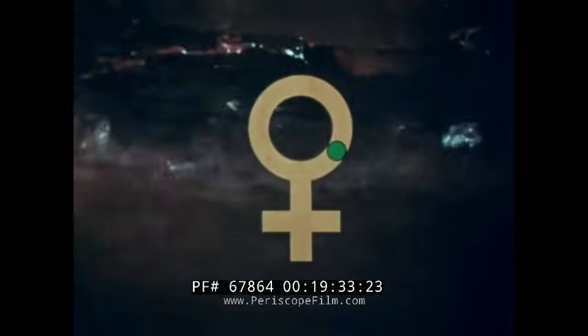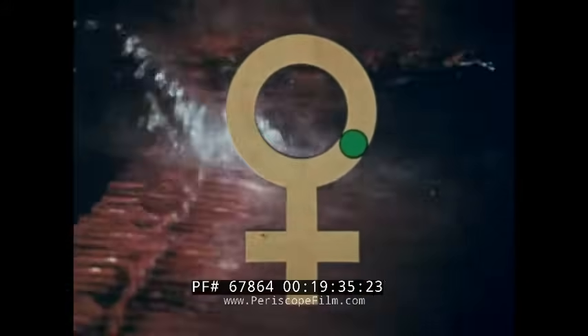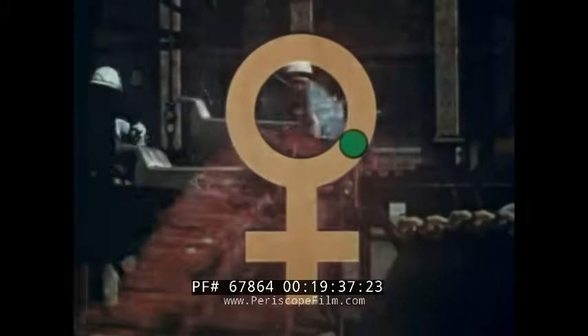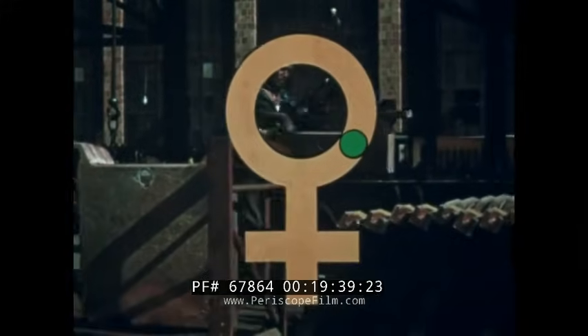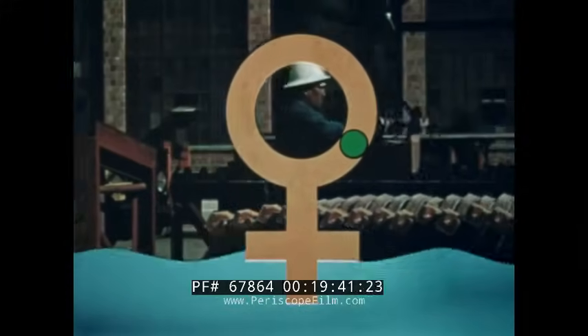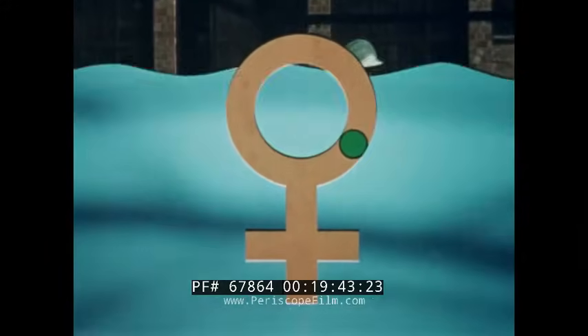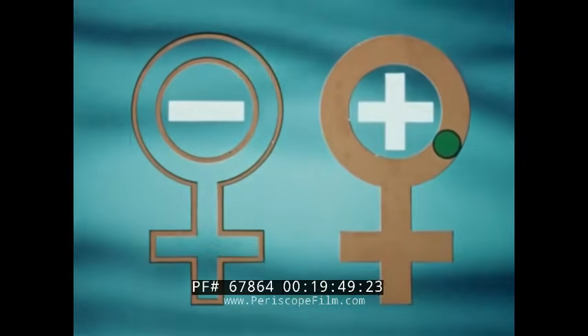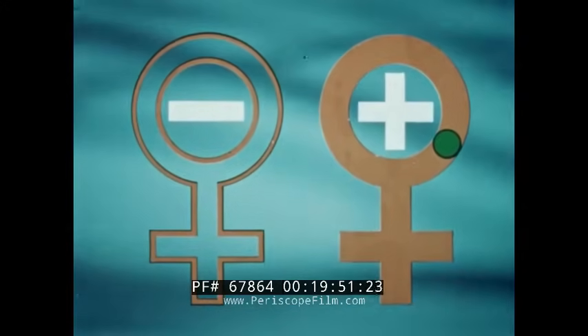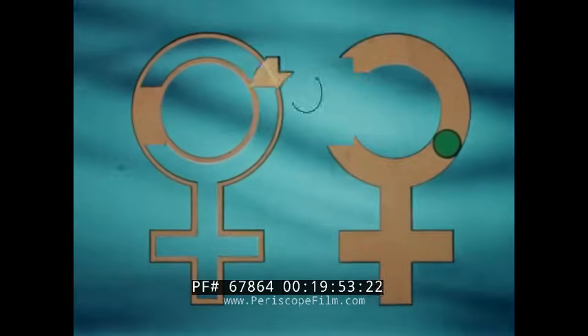The remaining impurities, including gold and silver, total only about 0.4%. These are removed by electrolysis. In the refining process, the copper anodes are submerged with cathodes of pure copper in a solution containing copper sulfate and sulfuric acid. As electric current passes through the cell, the anode is gradually etched away, and pure copper flows with the current and is deposited on the cathode.